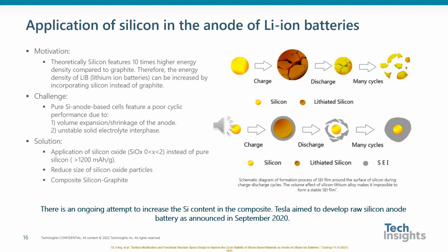However, there are challenges in using silicon as it is prone to significant volume expansion and contraction during charge and discharge cycles. These volume changes can cause cracking of the active materials and lead to an unstable solid electrolyte interface. These challenges have prevented silicon from being broadly used in commercial rechargeable lithium-ion batteries. To overcome this problem, several solutions have been introduced in the industry.